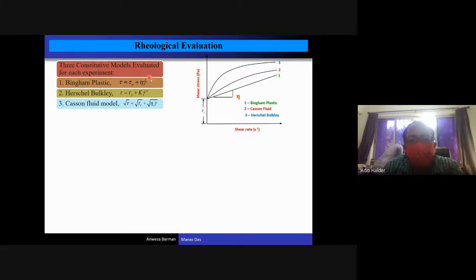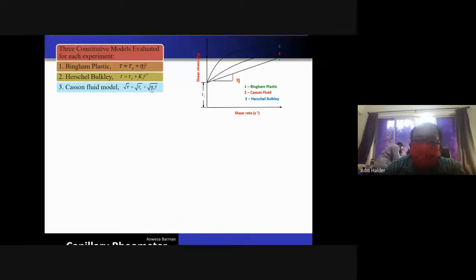So this is the Bingham plastic equation: tau equals tau y plus eta gamma dot, where tau is the shear stress, tau y is the yield stress of this fluid, which is inherent to the fluid, eta is the viscosity, and gamma dot is the shear rate. Now another fluid model which can also represent this MR fluid is called the Herschel-Bulkley fluid: tau equals tau y, the yield stress, plus consistency index K times gamma dot to the power n, the power law index. If n is 1, it becomes Bingham plastic. If n is greater than 1, it is shear thickening. If n is less than 1, it becomes a shear thinning fluid. So these are the three different fluids.